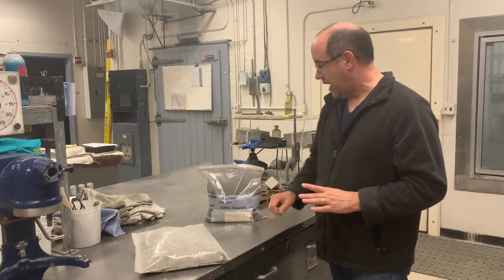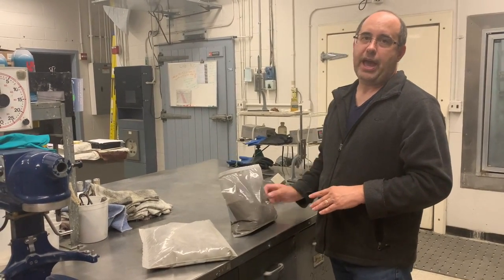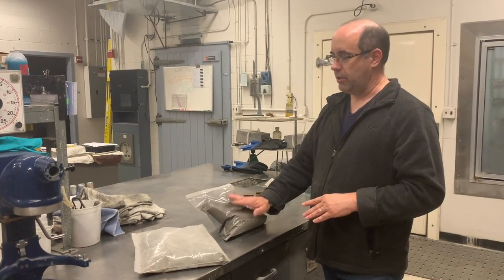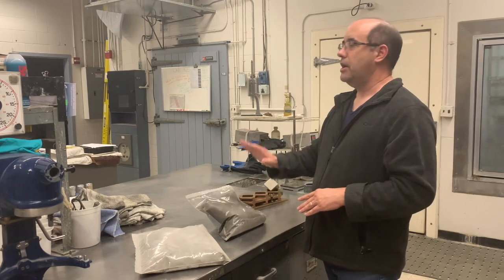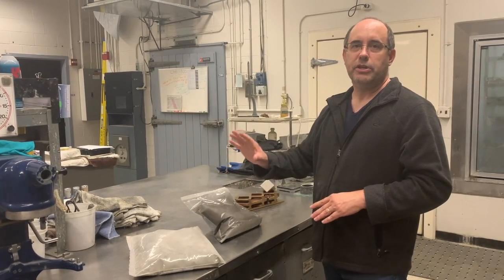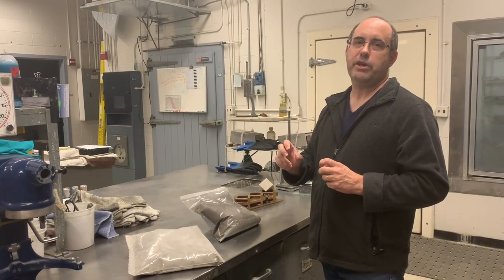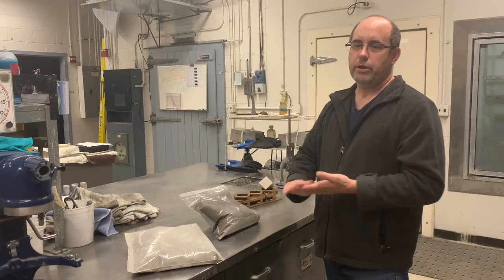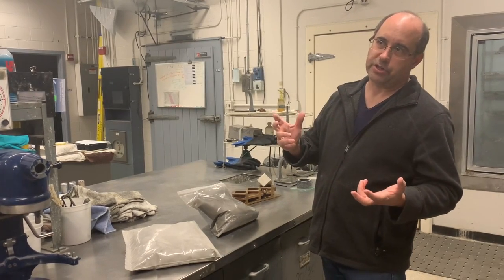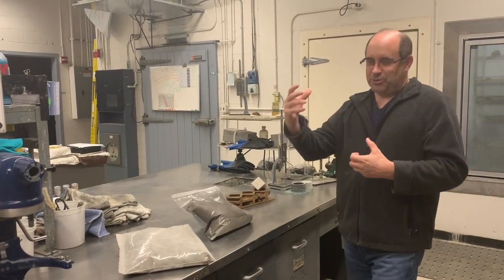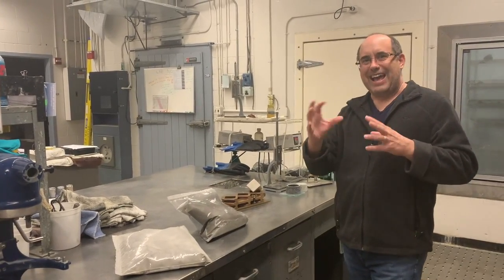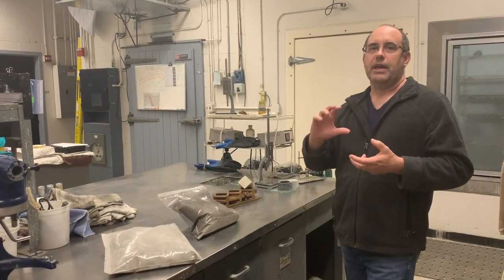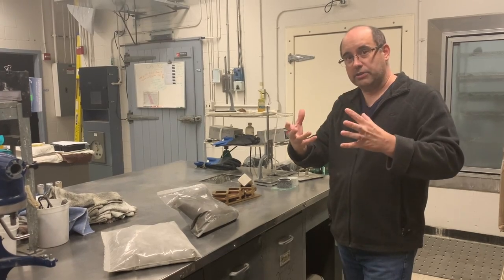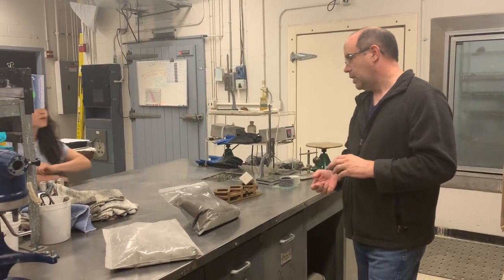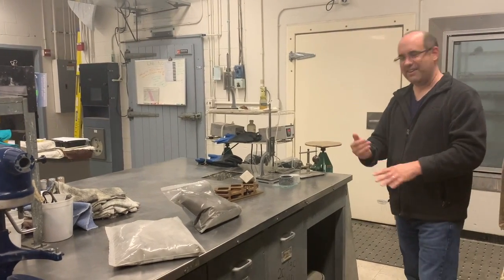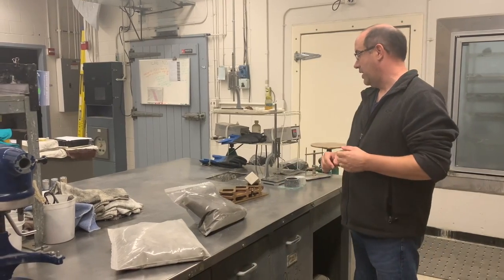So it's cement, and then this is a fly ash, which is the ash, the byproduct of coal burning. It's an ingredient in concrete that Caltrans requires. It makes for better concrete. It decreases the porosity of the concrete. It makes the concrete more resistant to something we call ASR, alkali silica reactivity, which is where the alkalis that come from cement react with the glassy elements of certain aggregate and create a gel which absorbs water, which then swells and can crack concrete apart. Cracks bad, because then everything gets in and things happen that we don't like.